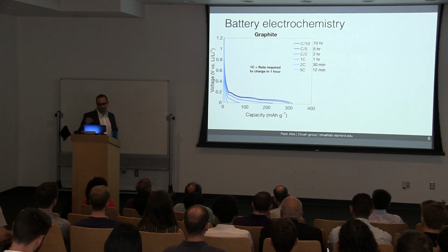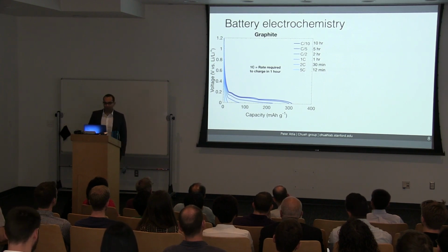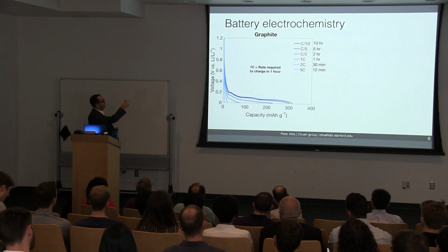As we charge faster and faster, we're unable to insert the same amount of lithium into the graphite, so the capacity decreases. Current is commonly expressed in terms of a normalized current called C rate, which is the rate required to charge in 1 hour.